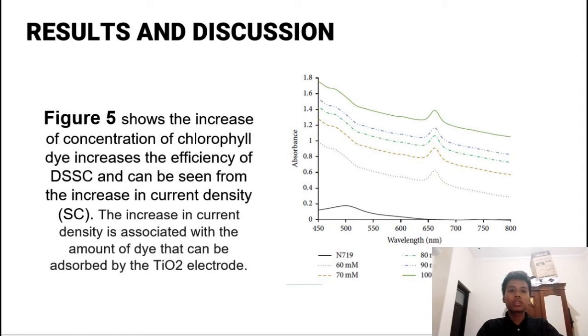This event gives rise to the possibility of some breakdown of titanium dioxide by the acidic carboxylic groups of the dye. The resultant titanium ions combine with the chlorophyll dyes to create insoluble complexes, which precipitate in the pores of the film.